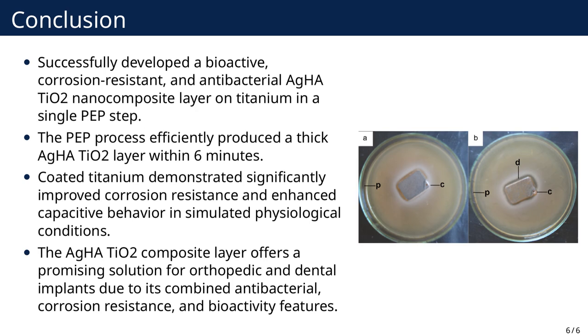A bioactive, corrosion-resistant, and antibacterial AgHA-TiO2 nanocomposite layer was successfully developed on CPTi in a single step using plasma electrolytic processing (PEP), a combination of plasma electrolytic oxidation (PEO) and electrophoretic deposition (EPD) techniques. The process yielded a relatively thick 83 micrometer AgHA-TiO2 layer within 6 minutes.